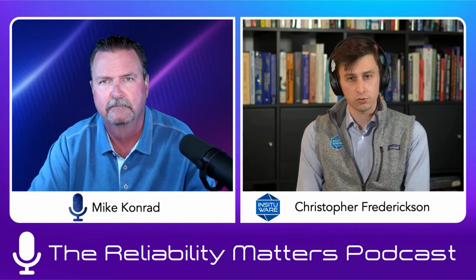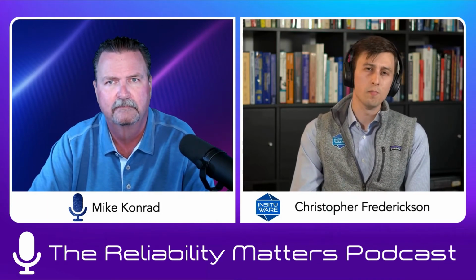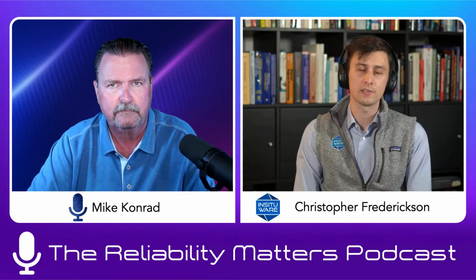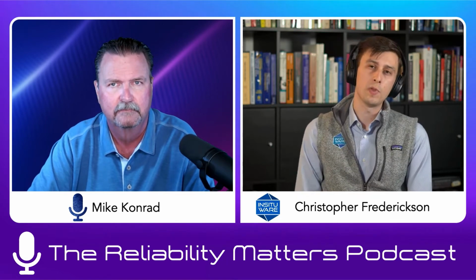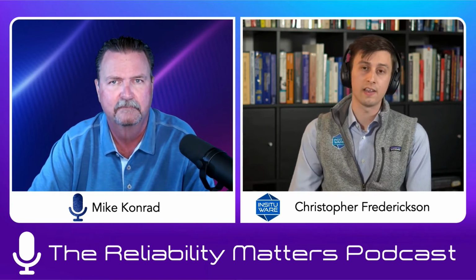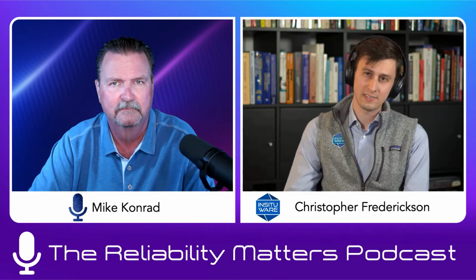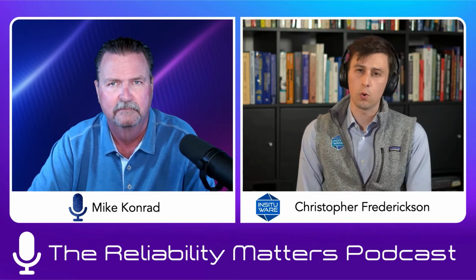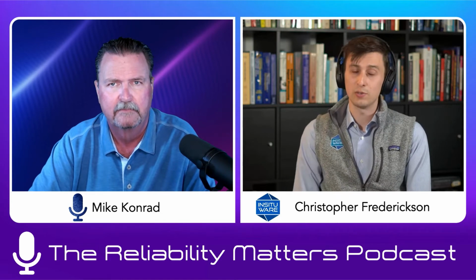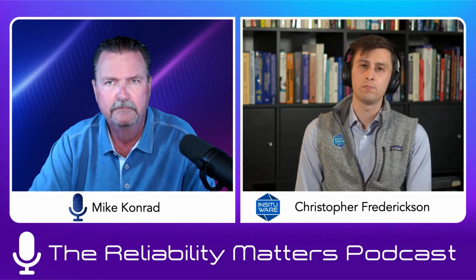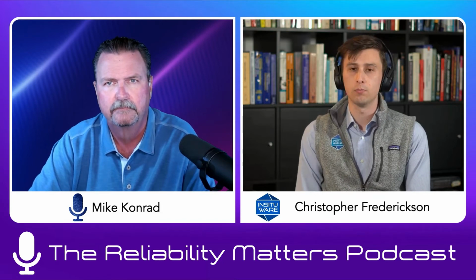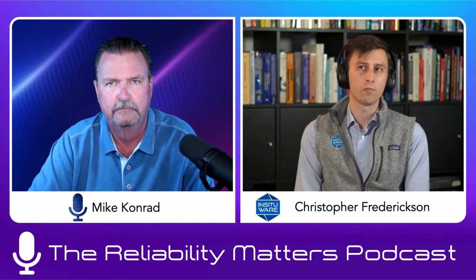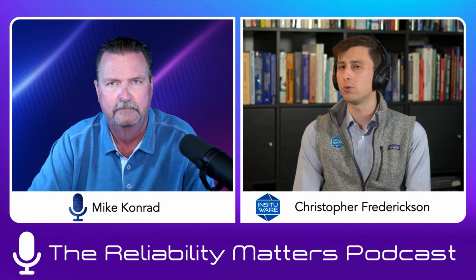You can measure the material just as it was received, but you'll get more variation due to the separation of the flux. You can measure it post stirring, and you'll be sensitive to both the material variation, but also the stirring process. So if it wasn't stirred fully, it'll be out of spec if you're setting it up that way. You can continue to stir it, see how that measurement changes to see if you're within your process window. Stirring absolutely is one of the areas where there still is a lot of manual process that doesn't have any sort of quality control step involved.